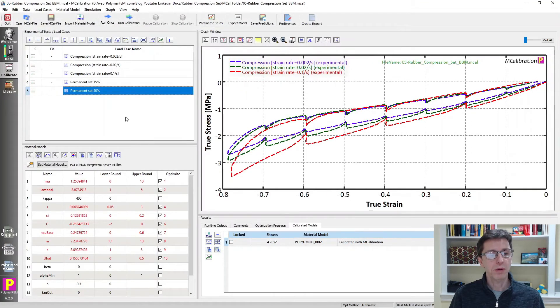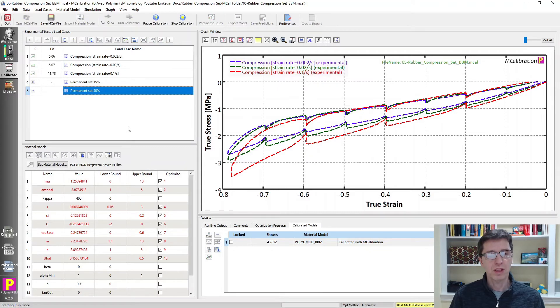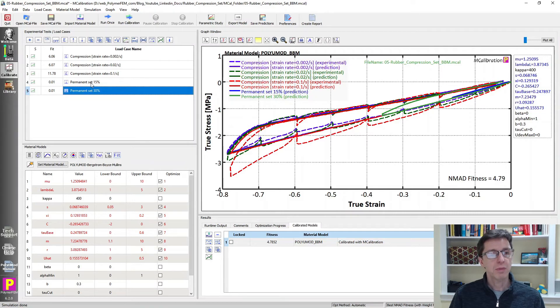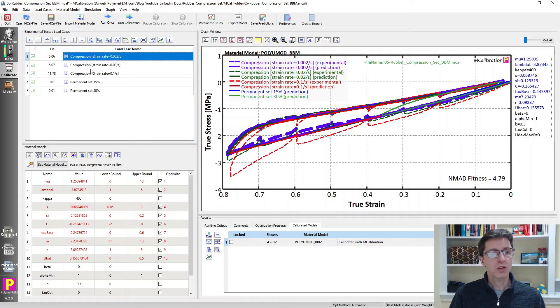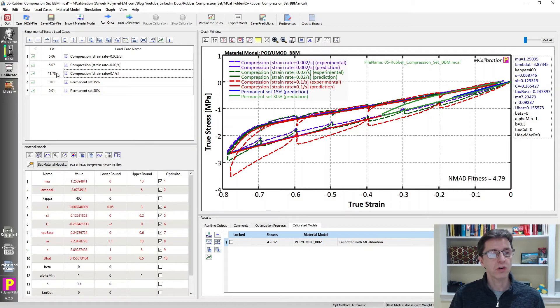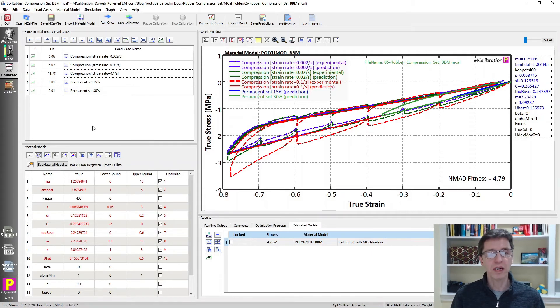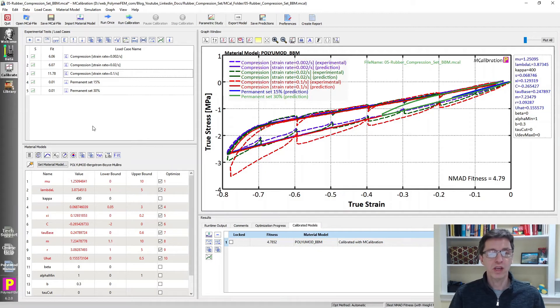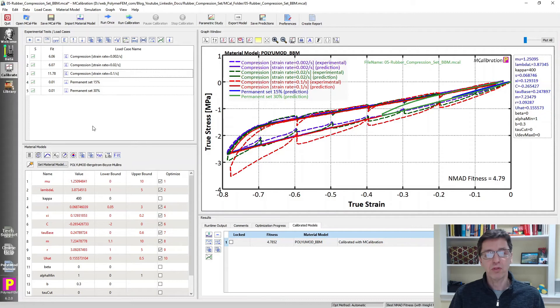What else can we do though? Well, it turns out that if you use the Bergstrom-Boyce model, but you activate Mullins damage. So here is the PolyUMod version of that Bergstrom-Boyce Mullins damage. When you calibrate that to the data, you will see that by doing that, you actually get really fantastic predictions. Now we have permanent set predictions that are perfect, basically perfect. And the cyclic data at different strain rates is very good too. The errors are small. On average, this type of model has an error that's 4.8% on average. And that's really good. That's kind of the order of experimental variability from one specimen to another. So this is often as good as you can get in terms of average error in the model prediction. So this is nice. This shows us that this actually is a strategy that works for this kind of problem.